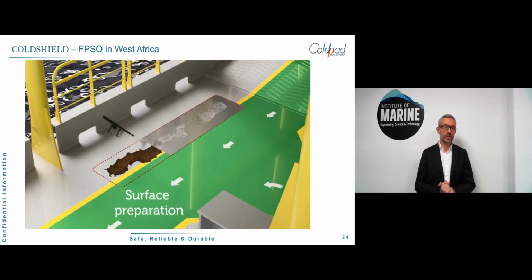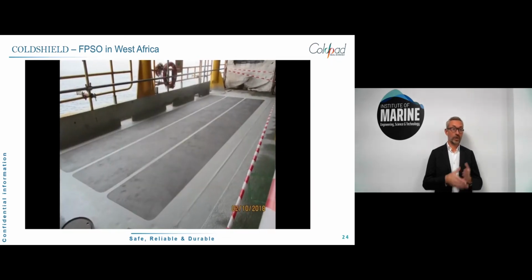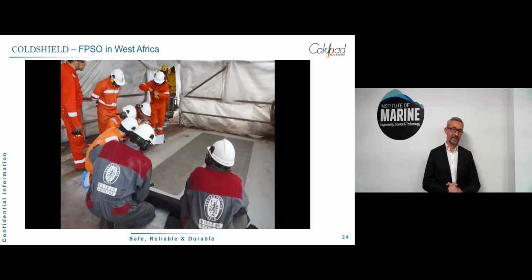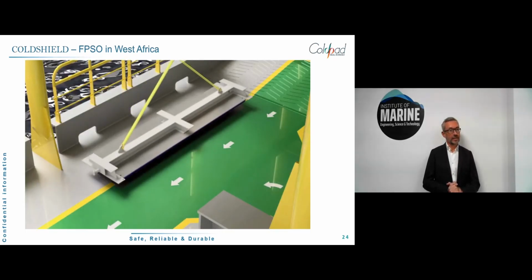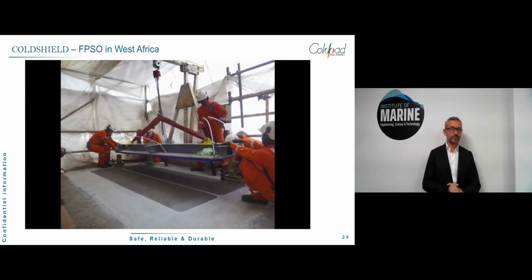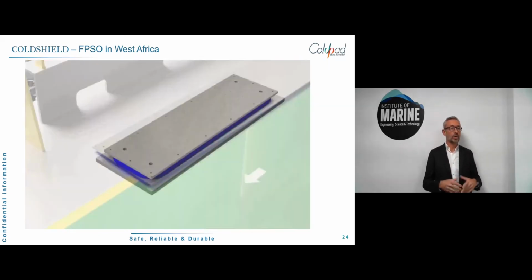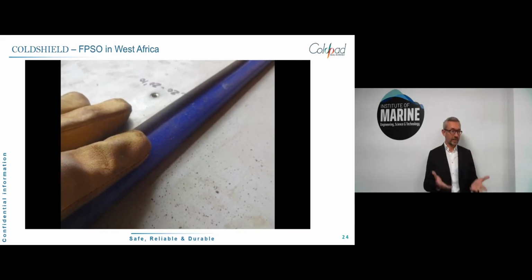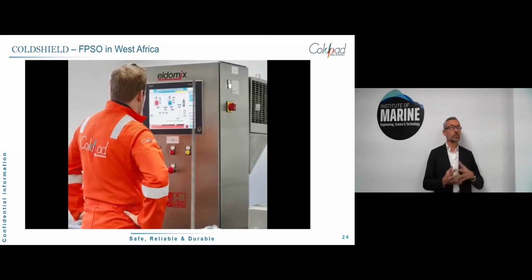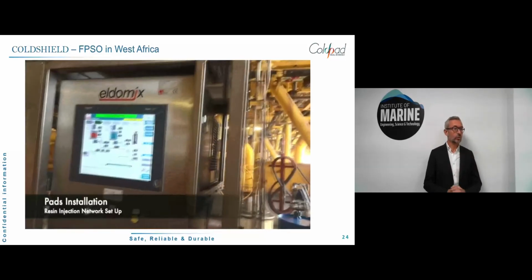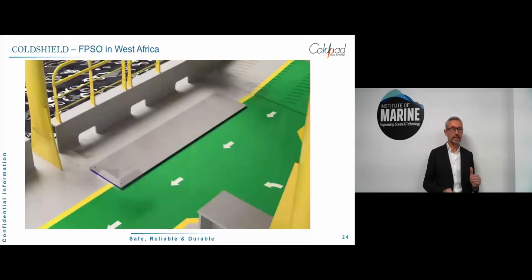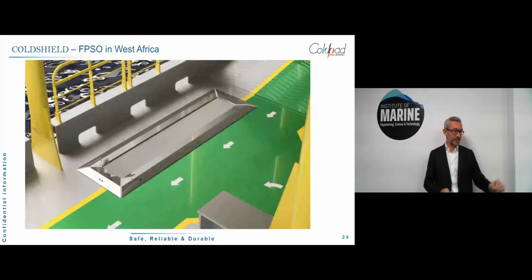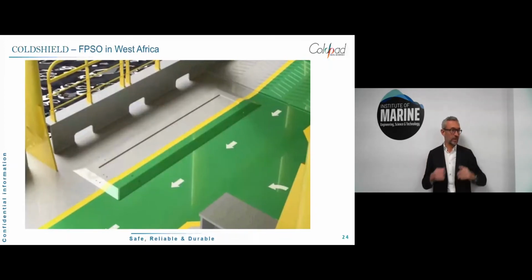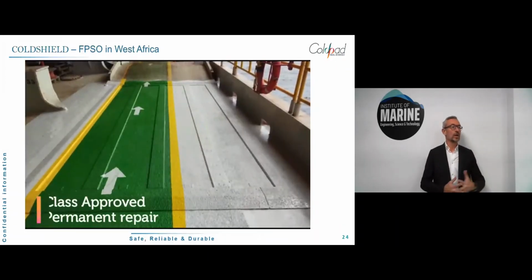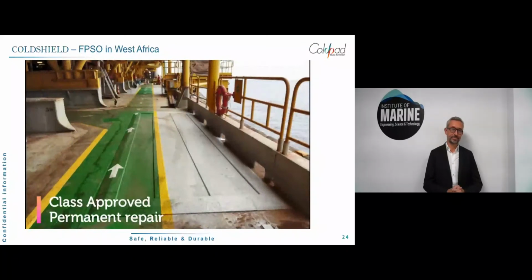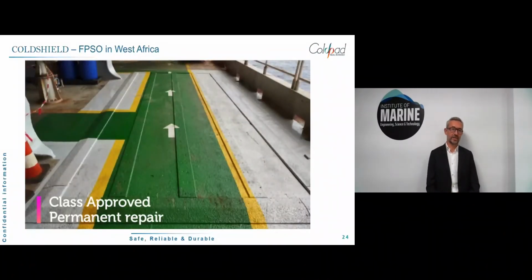So we do the surface preparation, as you can see. Once the surface is prepared, we have the painting and the naked steel. Then we install the reinforcements, and we do all the process that I've shown you: vacuum, dehydration, tightness control. You can see the seal, how much it is compressed, and then we use this robotic device to control all the parameters. What is interesting here is that every installation is done exactly the same. It's highly repeatable. We control all the parameters. It's always the same process, with the same vacuum, the same flow. And this is how it looks once it's installed.